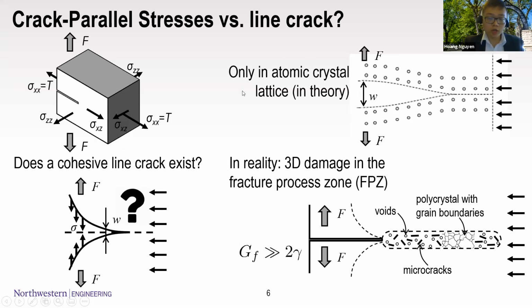And this is only true when you have a very sharp cleavage that goes through or cuts through the atomic bond. This strictly applies to the nanoscale only, when you have two sides of the crack being separated, or two sides of the atoms separated. However, in reality, damage or other mechanisms can happen. Like you have a damage zone or fracture process zone, and from now on I will refer to it as FPZ. Such a zone can appear at the crack, and when you have a crack parallel stress, it has an interaction with such a stress, and will have a certain effect on the fracture energy.